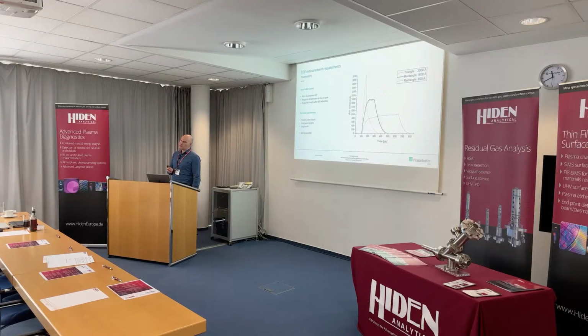We are very flexible with our arc discharge, and we heard about some low power sputtering processes before, and of course we have much higher powers. We have some 1600 amps, for example, at 80 volts or so. That means we have a lot of power in the system. And so also if we do the measurements later with the EQP, we have to reduce the frequency, otherwise we heat it up, and so we can only measure for a short time. This is something we always have to think about. There are many different aspects we have to think about if we want to get decent measurements out of it.